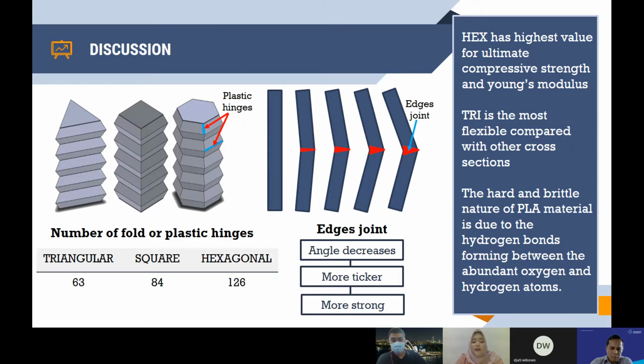Therefore, the hexagonal specimen has the highest ultimate compressive strength and Young's modulus due to the number of folds or plastic hinges and the average thickness that is more than the other specimens, so they can withstand more stress. The average thickness of the triangular is lower than the other specimens due to the number of folds or plastic hinges, so the ultimate compressive value of the triangular specimen is the lowest compared to the others. And 3D printed PLA shows brittle characteristics due to the hydrogen bonds forming between its abundant oxygen and hydrogen atoms.